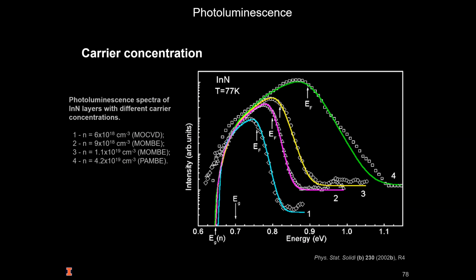Here, the process was just reversed, so they had some known carrier concentration for several samples, and they combined that with photoluminescence to determine the band gap energy of their sample, indium nitride. The solid lines here are theoretical fitting curves based on a model of interband recombination in the degenerate semiconductors. With these fits, the authors determined the band gap of indium nitride to be about 700 millielectron volts.